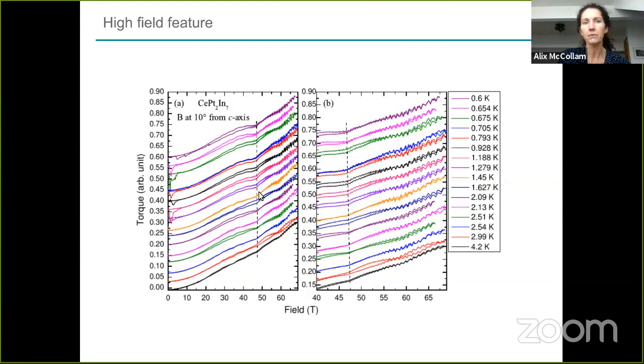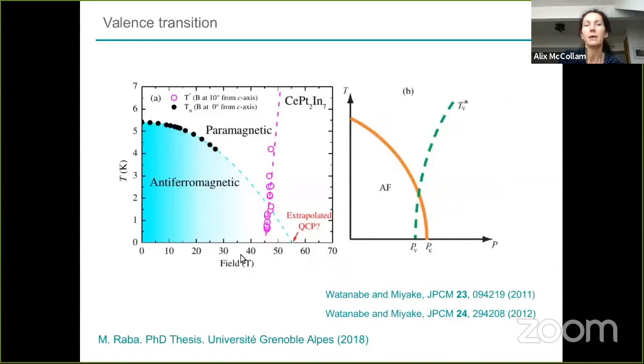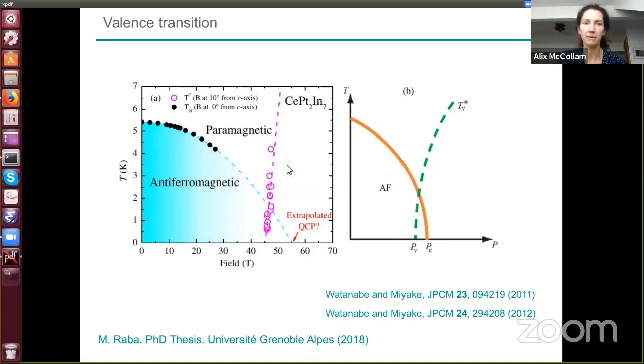So this corresponds to the feature in the tunnel diode measurements that was thought perhaps to be a Lifshitz transition, so a change of the Fermi surface from localized to itinerant, so from large to small. But we see that there's very little temperature dependence, and we've also seen that there's no change of the Fermi surface across this transition, but it still leaves the question as to what that is. If we plot it on the phase diagram, this is cerium platinum 2 indium 7, temperature of that feature at around 45 Tesla. You see it's very weakly temperature dependent.